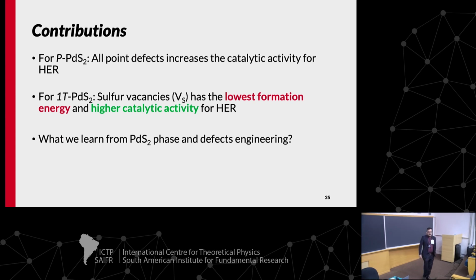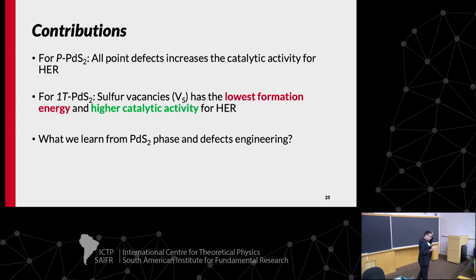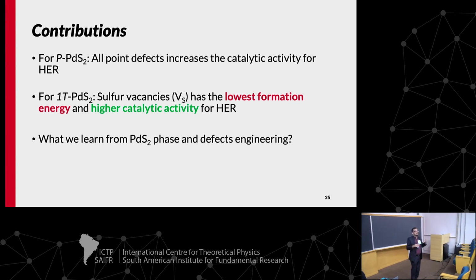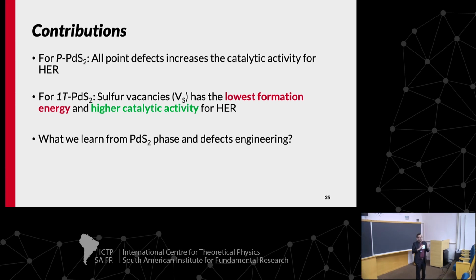Yes, we have a correlation with the edge length for the hydrogen evolution reaction, and actually it's because of the bonds of the exposed molybdenum. But even different edges have similar behavior. In this case, we have different edges, but with high activities too. So it's not only the dangling bond. Maybe it's a collective effect for the edge.